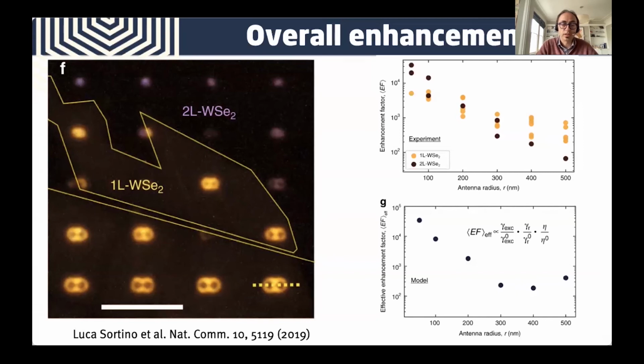On the left, I'm plotting the confocal scan that you can do over the sample. You see that the antennas are in different parts of the sample, and on top you see the layers, the one layer and the bilayer. And you see that the enhancement is very clear. Even visually, you see that there is a lot more light coming out of the sample.